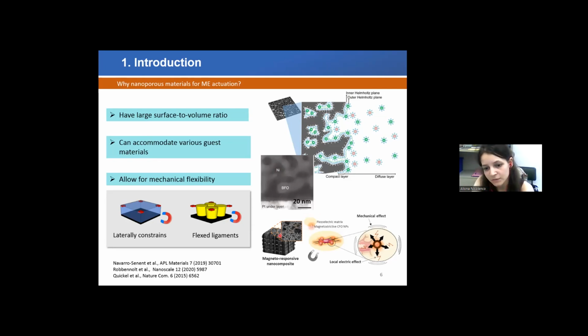Or in this case, for example, we have a polymer, a piezoelectric polymer, that is filled with magnetostrictive cobalt ferrite nanoparticles. And in this work, they targeted again some composite materials where the magnetoelectric effect can be induced locally with the external magnetic field. Then, interestingly, the nanoporosity can also bring some mechanical flexibility to the films.